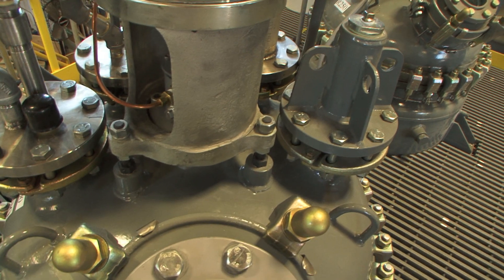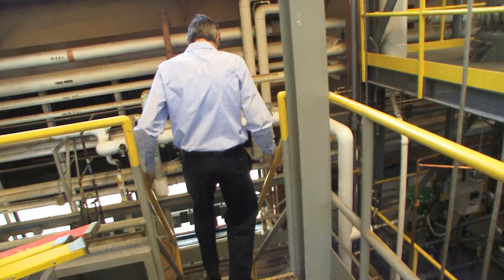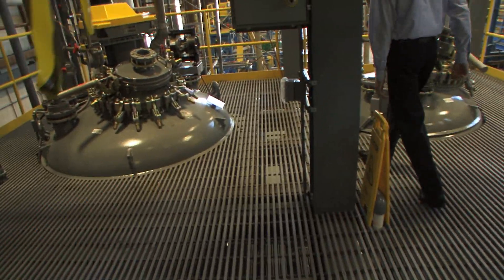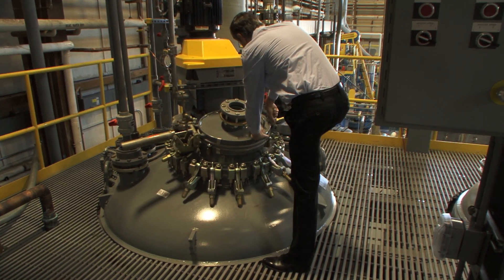The pilot plant is built on three levels. These first two reactors are 100 gallons each. We are using one primarily to make cellulose nanocrystals. To do this, we take shredded pulp and load the vessel up with it. Then we pump 64% sulfuric acid through some spray nozzles as the agitator turns the bundle of pulp. The reaction is over in about two hours. We open a valve at the bottom and the slurry drops from this deck down 10 feet to a larger reactor just below us. That reactor is 1,500 gallons.